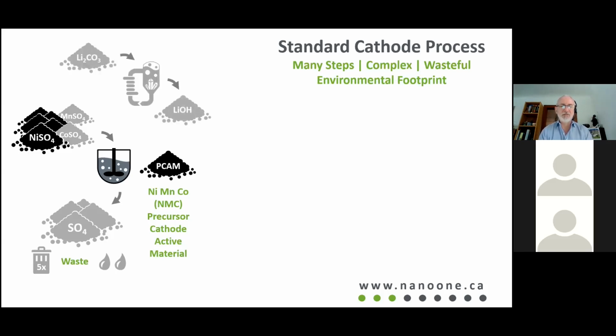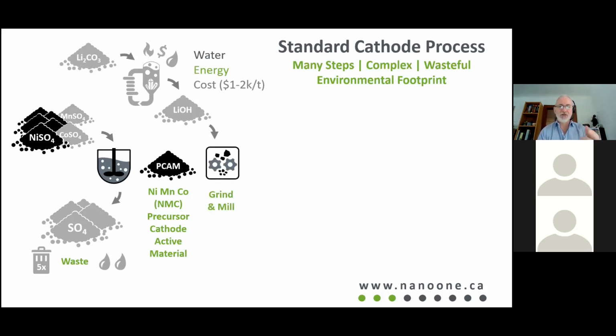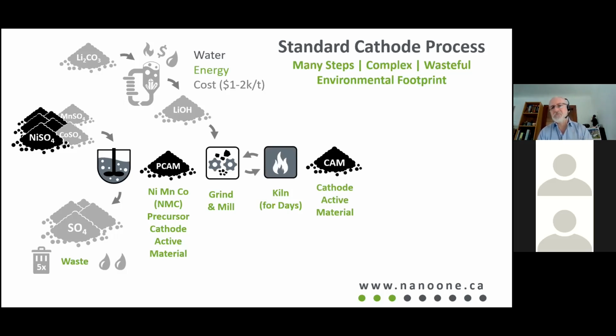And then you add the lithium. Now, the lithium for high nickel materials has to be lithium hydroxide. So if you're making lithium carbonate in a salar in Argentina, I'm sorry, you have to convert it to lithium hydroxide before you can feed it in, which also has costs and uses a lot of water. And then you grind the lithium hydroxide with the PCAM together in a mill, and you feed it into the kiln, and you fire it in the kiln for roughly a day, and then you have to grind it up again and then fire it again, and do this 2 or 3 times before you finally get your cathode active material.